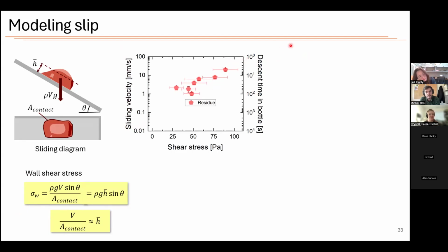So in general, if you have a lot of ketchup or a high angle, this results in a high shear stress, and you always have cases where you leave residue as the ketchup falls. You get to a lower level that's close to the bounds of the yield stress, where some ketchup yields and some of it doesn't. Rather than a very thick layer of ketchup left behind, you leave maybe just a few spots of residue. This is probably because of the surface structure of the bottle, which might have some imperfections or little spots. The most interesting case is if the shear stress is low enough, then you actually have ketchup that flows and leaves no residue. In the ideal case, you would be able to use this and get all of the ketchup out of the bottle without any residue. But the very sad point is these only occur very, very slowly, which means that you would have to wait minutes or hours for the ketchup to come out.